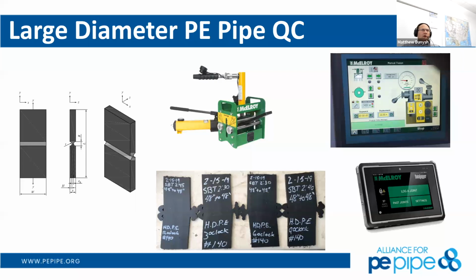And so this little diagram to the right shows that as you get to thicker wall thickness, it changes the physics of the welding operation, meaning that when you look at joining the two pieces together, the material in the center of the wall thickness has such a larger distance to travel. And that travel distance with time gives you the speed. Speed is not the friend for molten plastic. It likes to meander very slowly in a more laminar flow. When you start to increase that pressure of the weld, you get velocities that exceed the fusion pressure and time under pressure.